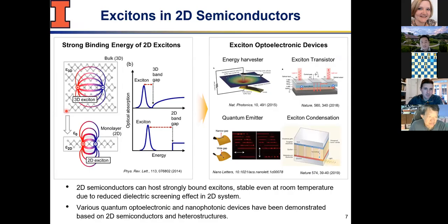So let's get started. Before I get started, I just want to talk about the light particle I mentioned in the 2D semiconductor. So this is a one layer thick, or I should say three atom thick. For example, tungsten selenide is one of the materials that we're going to look at. You have a mid-plane of tungsten, and you have sulfur, or selenium, sorry, in this case on top and bottom. So it's a three-atom thick semiconductor. And it's a so-called direct gap semiconductor. So the optical transition is direct in momentum space. What that means in real life is when you shine light, the transition is very, very efficient.